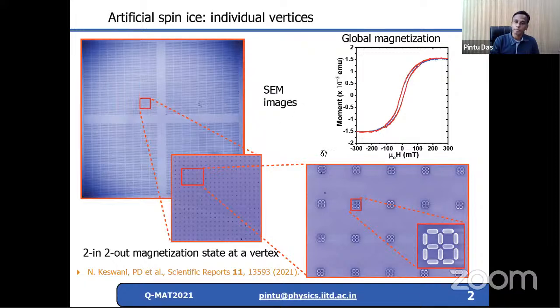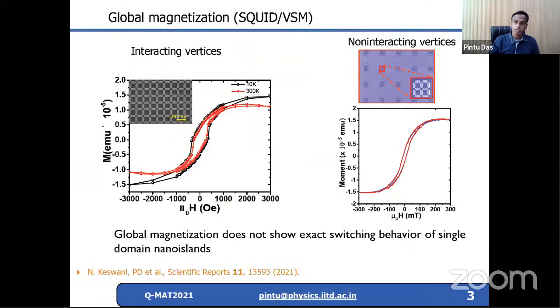If you want to study this switching behavior, say by performing global magnetization measurements, what you see here on the screen is a large number of square artificial spin ice vertices. If you perform a global magnetization measurement, you typically see these kinds of hysteresis loops. Of course, they are related to the switchings of the individual shape anisotropic nanomagnets, but you cannot get any proper information regarding the switching behavior. What I showed earlier is unconnected vertices, meaning non-interacting vertices, and this is similar even for interacting vertices. So you do not get much information about the switching behavior.